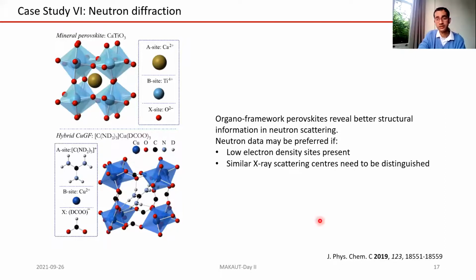Another important thing is that these people took copper at this site, and then replaced copper with, for those of you who are aware of the periodic table, manganese, iron, cobalt, nickel, copper, zinc. So they had a play around with these 3D transition metal elements and replaced this copper with manganese, iron, nickel, zinc. I think they did manganese, iron, and nickel. And those are very close to each other. Because they're very close to each other in the periodic table, their electron numbers are very similar and their X-ray diffraction properties are similar. But their neutron diffraction properties are different. So they used neutron diffraction. What I'm trying to say here is that instead of X-ray diffraction, you can also use neutron diffraction, given that the electron densities are low, such as in proteins which have a lot of carbon, hydrogen, oxygen in them, or if you have similar X-ray scattering centers present.